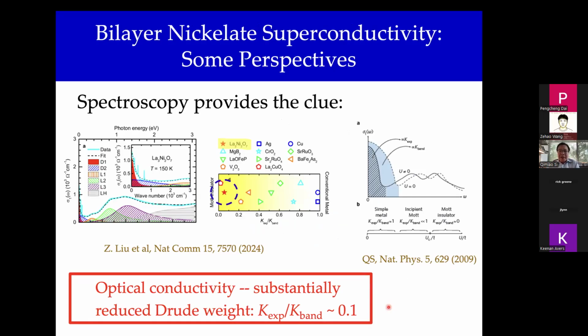So this is a general consideration, and at the very beginning, there were very few characterizations of the system. What there was at ambient pressure, and I want to single out this measurement from Haihu on the optical conductivity, because it played a very important role in our thinking about the problem. And so this is the optical conductivity, sigma 1 omega versus omega, and put in here are some band structure calculation results based on the DFT calculations, and then there's a measurement.